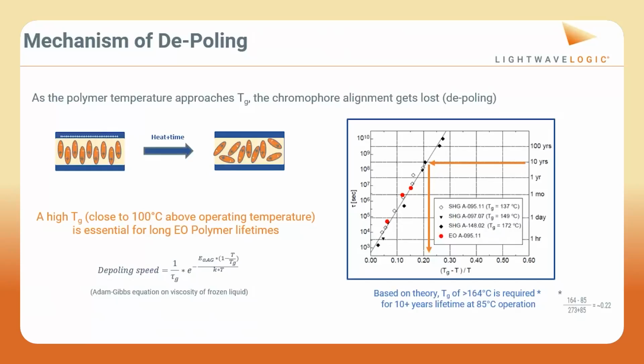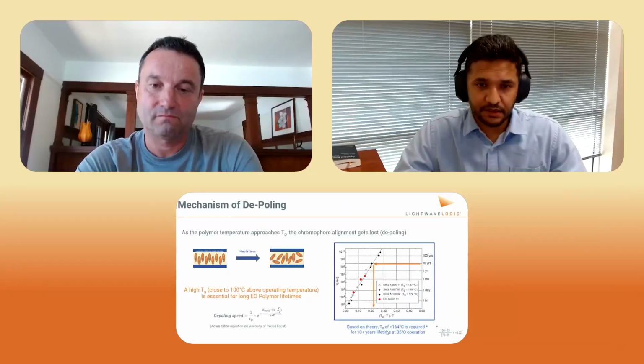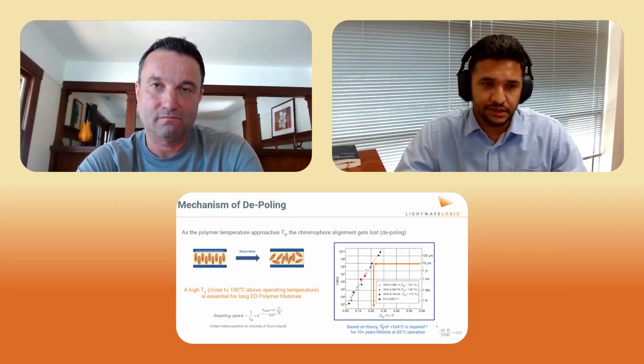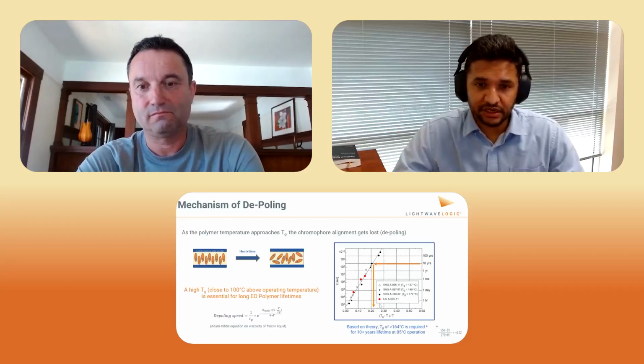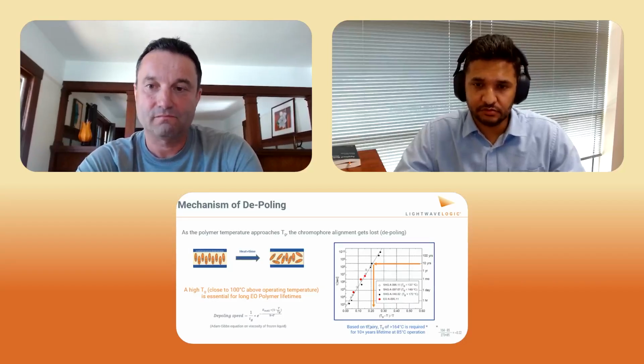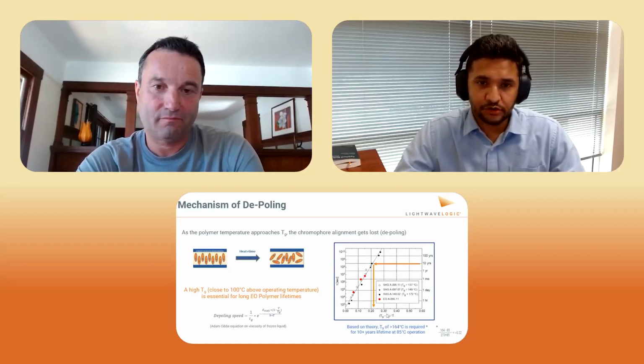And what we did is we actually solved for this equation, and we found that if you want to survive more than 10 years without significant depoling at 85C, then you need a Tg that is above 164C. So that's the minimum that you need to survive more than 10 years at 85C. What we've done here is we've engineered our chromophores to have 185C or more Tg, which gives you a much bigger margin than what you actually need.